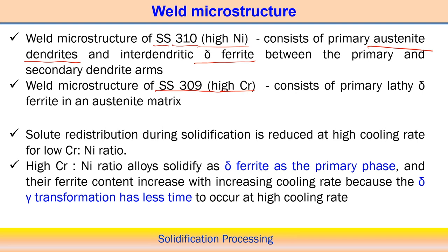So the nickel content is high in the case of SS310 stainless steel, but if you see a change of composition, high chromium content in the case of SS309, that particular grade of stainless steel, we can see it consists of primary lathy delta ferrite within the austenitic matrix. So here you see that when there is a change in the composition, nickel or chromium, the dendritic structures are different in these two cases. Similarly, we can see that